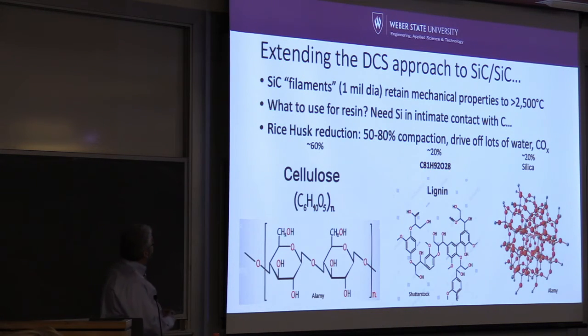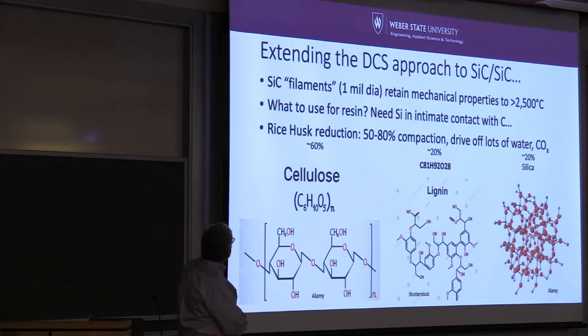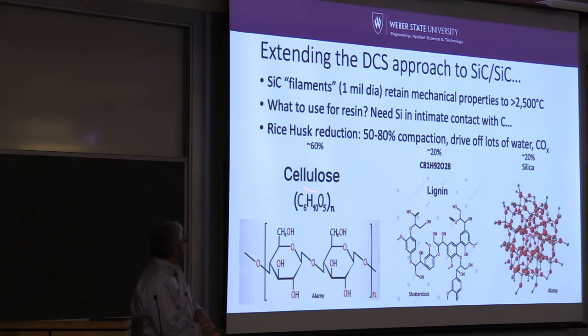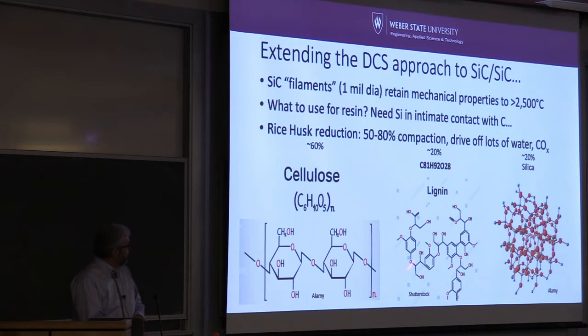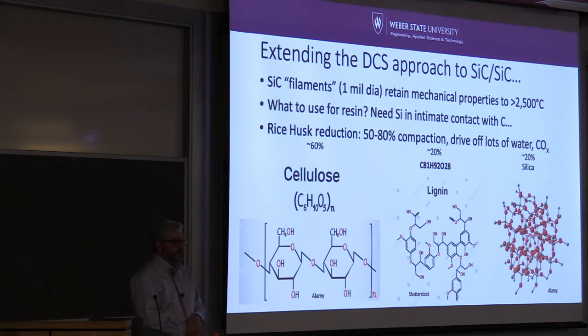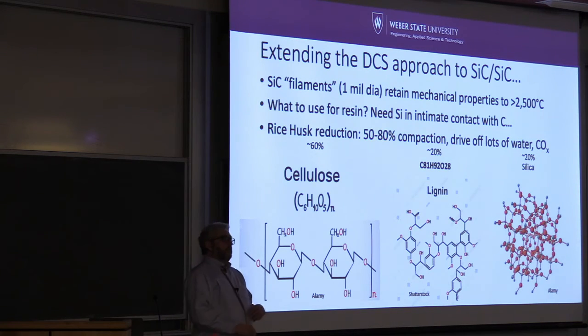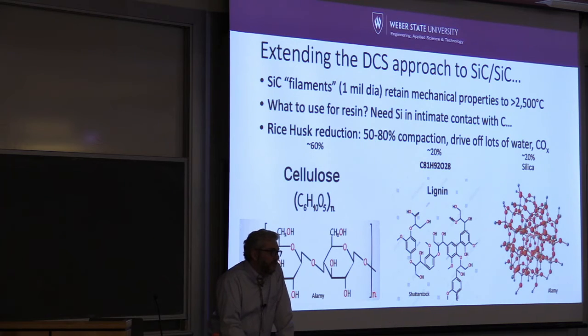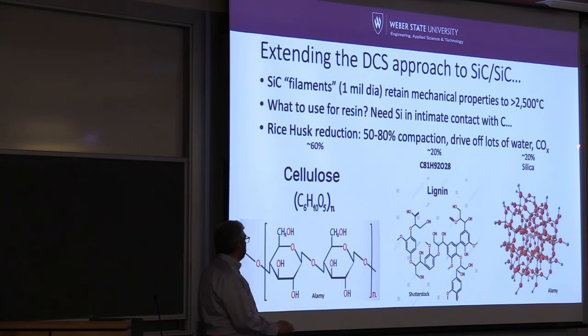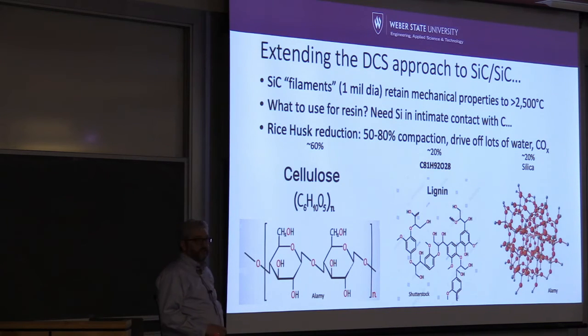So let's take a look at one approach. So here's the rice husk. The rice husk is maybe, and these are rough numbers, and it depends, but 60% cellulose, 20% of this lignin, silica. So the direct current sintering technique relies on electrical conductivity. What can we say about electrical conductivity based on these constituents? What about silica? Conductive or not conductive? Okay, thumbs down, right? So that's glass. It's not conductive.